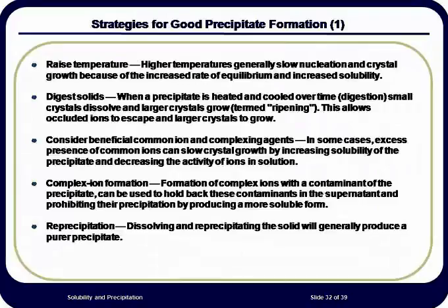The precipitate can be digested to improve its crystalline structure and remove impurities. Digestion can be done by heating the precipitate with its supernatant after it is formed, or by allowing the precipitate to equilibrate at room temperature with its supernatant over the course of several hours to a day.